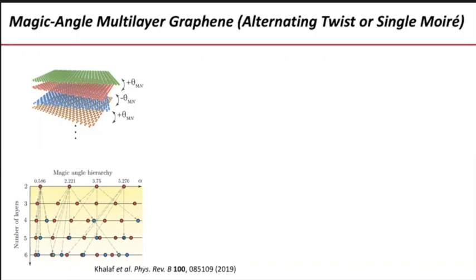So for two layers, you have the first magic angle, which is this 1.1 degrees. Then there is a second, third, fourth magic angle. No one has seen those experimentally, but they're predicted. We don't know if they're stable. We know that the first one is stable. Then for three layers, you also have first, second, third magic angle, et cetera. Starting from four layers, you have the first magic angle, the second first magic angle, but you also have the first second magic angle, et cetera. There's a hierarchy, a tree, of electronic structures that happen for different angles, in which you always have a flat band and then additional electronic structure.